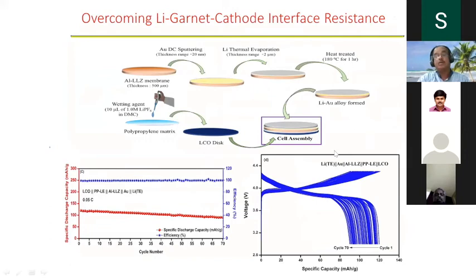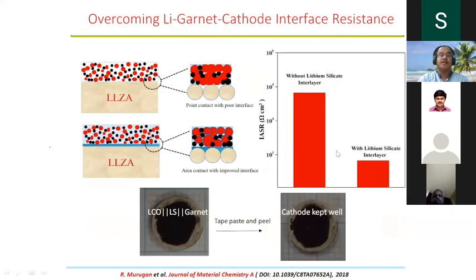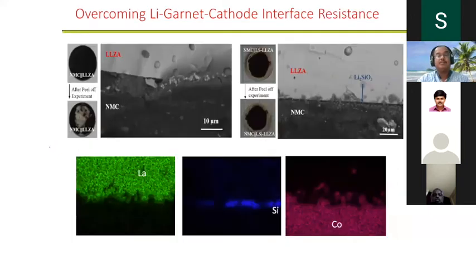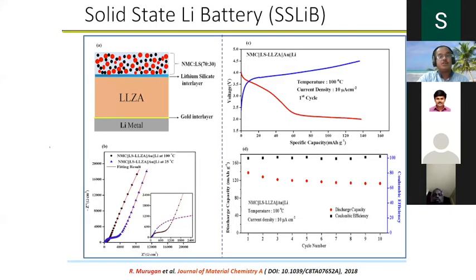Then we have done several works throughout the world. People have done a lot of work regarding this. This is another way of overcoming it, by means of an area contact with improved interface. You can see here, without the lithium silicate layer and with the lithium silicate layer, we introduced one layer of lithium silicate and put the LCO on it. Its binding is so good that it gives better cycling efficiency. But I don't think it can match present-day liquid electrolyte batteries. The interface is not so great. Slowly we are improving the cathode-garnet interfacial issues.